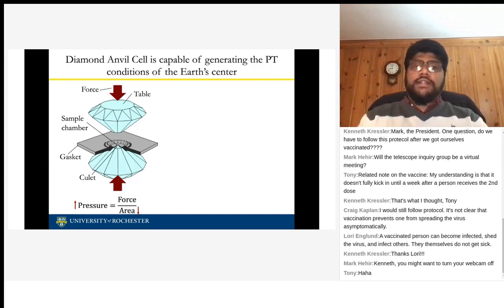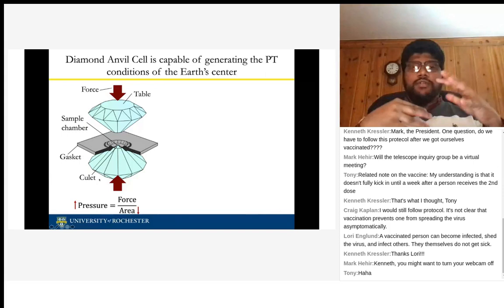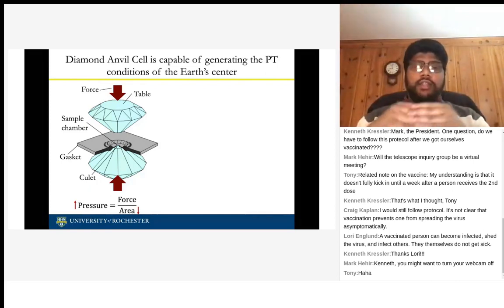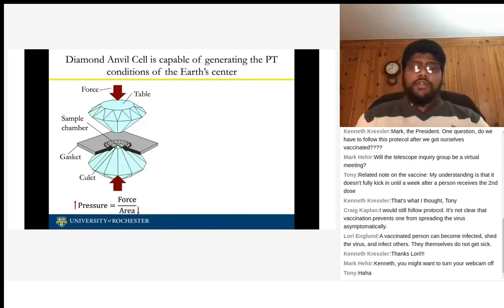So this is one way we can generate high pressure. We call it static compression, because this way you have all the time in the world to study the material. Because diamond is transparent, you can see through the diamond. You can shine a laser light. You can apply any other technique to characterize the material's properties, X-ray or even neutron diffraction. Anything you want to do, you can try through this material as well. So this is why the diamond anvil cell is a little bit special, because you have a lot of opportunities to characterize the material.